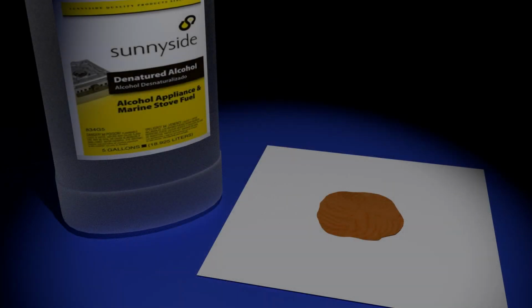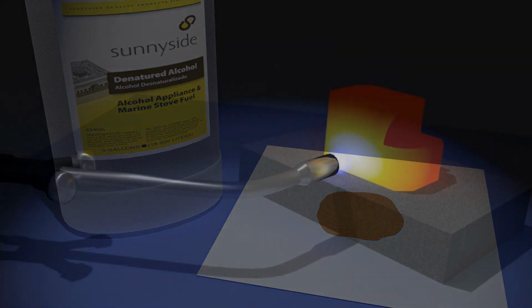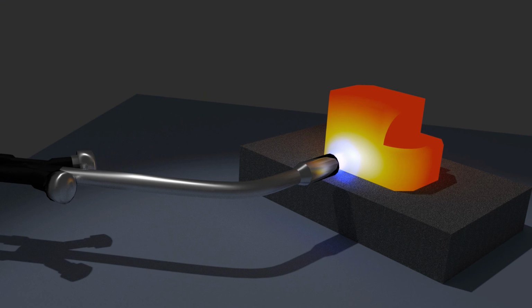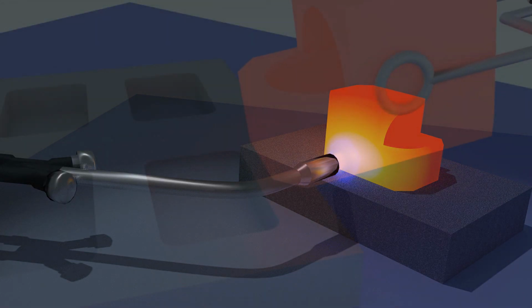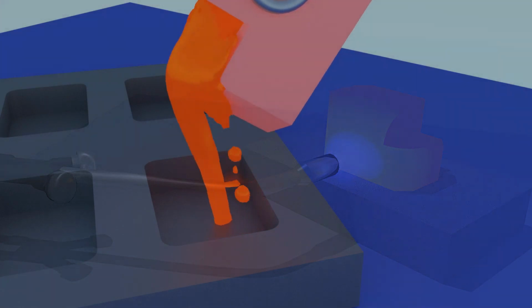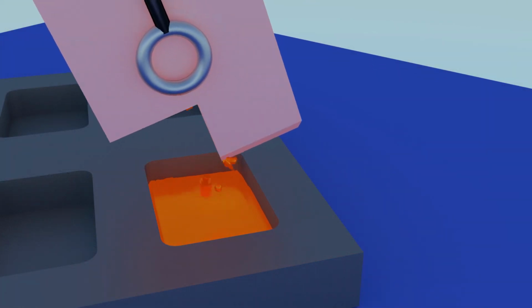Wrap your gold powder in jeweler's tissue paper. If that is not available, you can use a small section of a paper towel. Soak the wrapped gold powder in alcohol, and place it in your crucible. The paper and alcohol will help secure the powder, so that the air currents produced by the torch flame don't blow it away. Both paper and alcohol will burn away, leaving no trace. Melt your metal. When it flows like water, pour it into an ingot mold to make a bar of gold, or pour it into ice water to make shot.